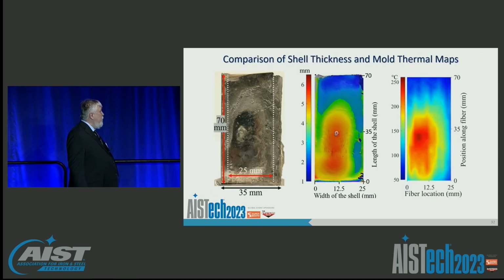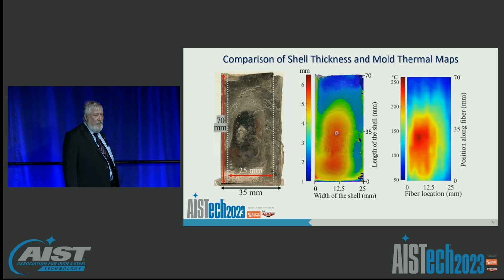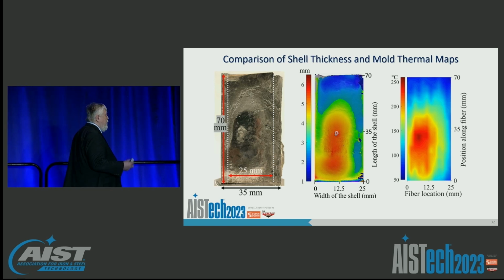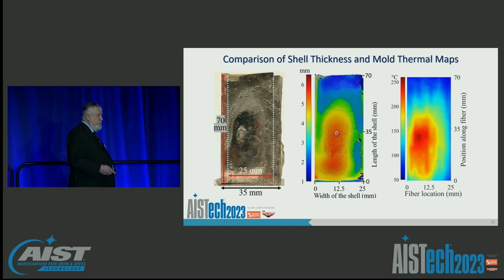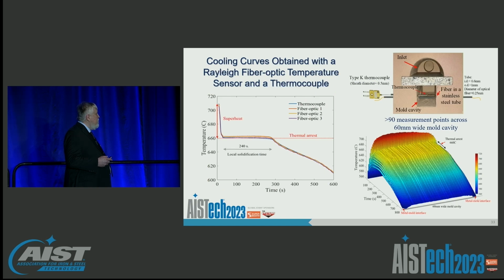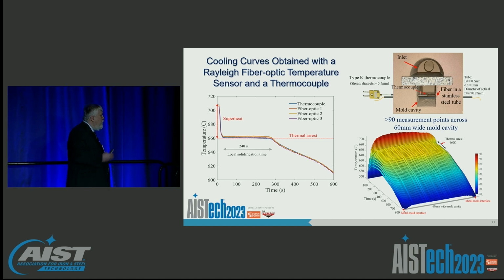Just to give you an idea of the resolution of these systems, there's a shell profile, and the thickness profile corresponds very well with the thermal mapping profile. And so we're actually able to get very high detailed information in this type of sensing environment. So these fibers are good up to about 700 C, and in this environment, we can actually use them in other processes as well.